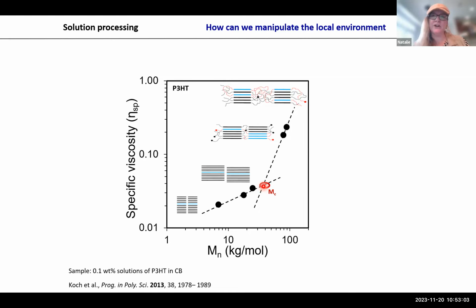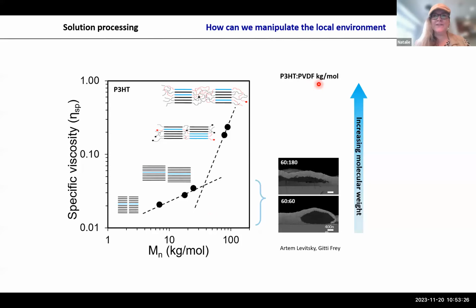And you see you have an inflection point, and that's the point where we hit the critical molecular weight where you start to have entanglements, knots, like in the hair. And that means here in this area, you have much less diffusion, so mass transport is much lower. And we really call high molecular weight materials once they have reached this critical molecular weight. These guys we call low molecular weight. And once you go blending, this is really important.